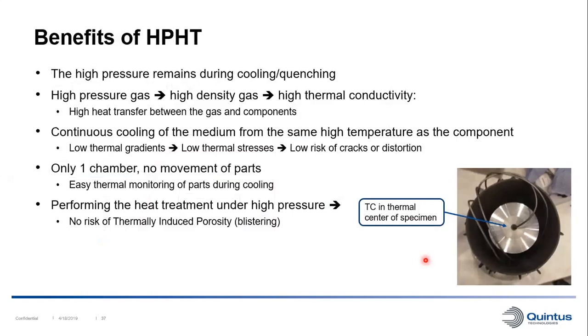Also, the components and the pressure medium start at the same temperature when we are performing our heat treatment. So we start cooling the pressure medium, and then the components will follow. So it's a little bit softer quenching compared to a water or an oil bath quenching, where you have this initial thermal shock in the beginning. So with this process, we get low thermal gradients, low thermal stresses, and a low risk of crack and distortion during the quenching of our parts.